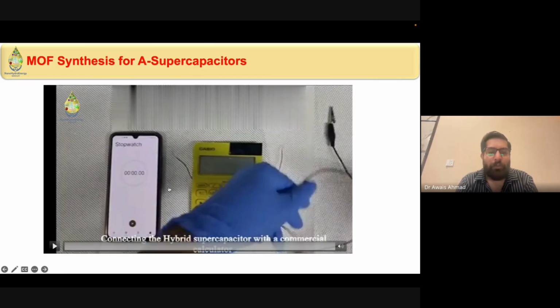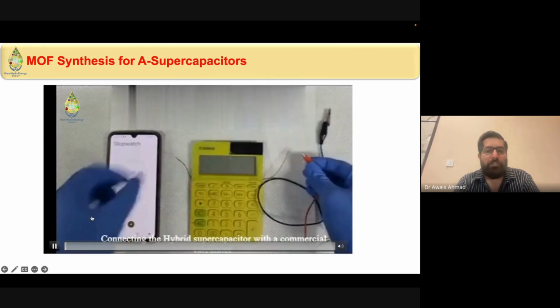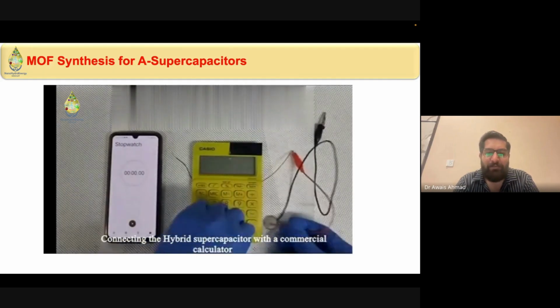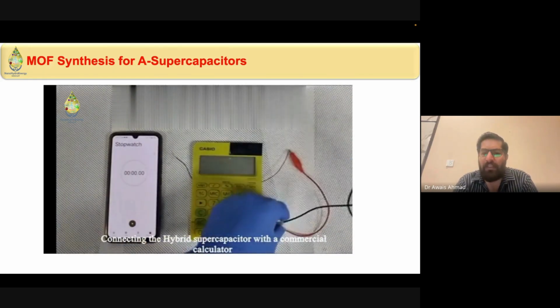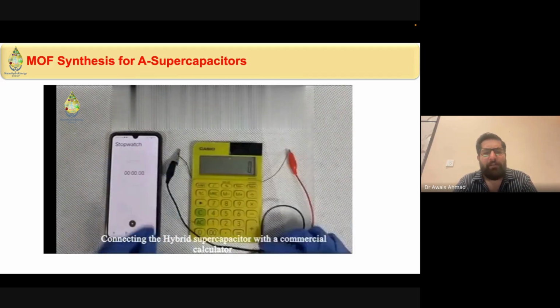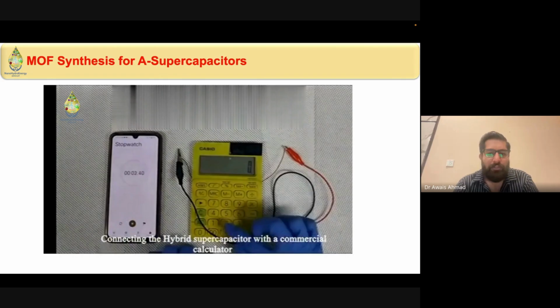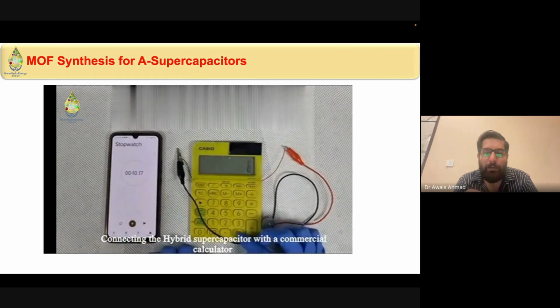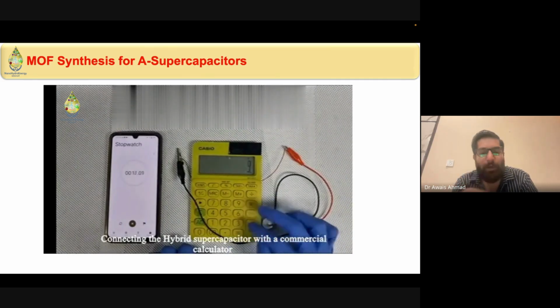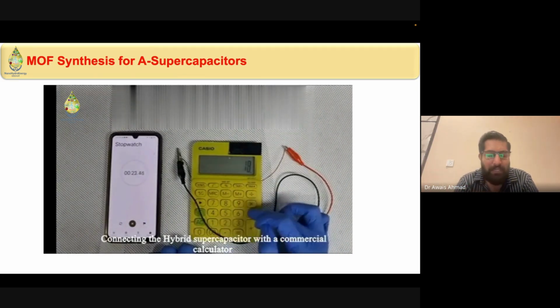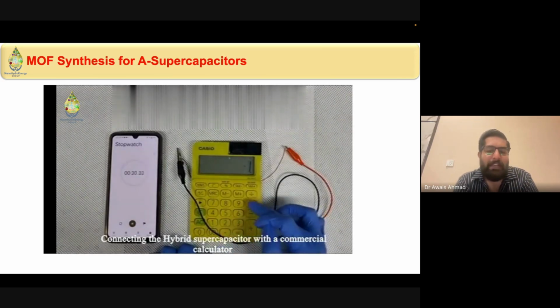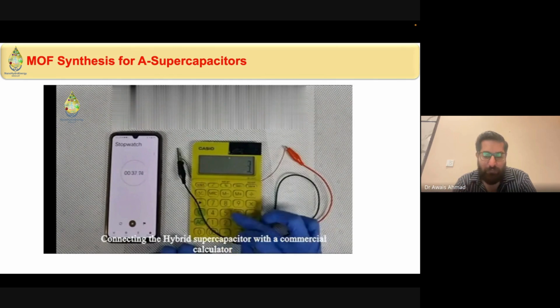And here is a little video which will be really inspiring, that we designed this material, and at the end we tested this material in our coin cell application, a real cell application. It was a project with Casio. So just watch this video. So here we just incorporate our coin cell with a simple Casio calculator, because your coin cell will not be wasted, it can be charged every time. So now you can see that the calculator is working with the help of this coin cell, and this coin cell can be charged more than 1,000 times and can work for almost 10 to 15 days with one charge.